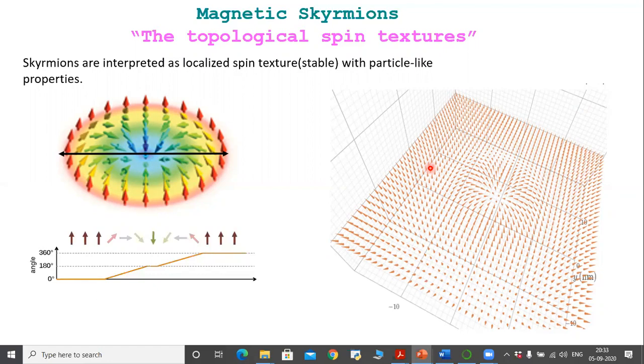Okay. So you are using a 2D film, I mean, only one layer of spin? Yes, one layer of film. This is actually a Néel skyrmion, found only in 2D films. There is another type of skyrmion called the Bloch skyrmion, which is found in bulk materials. Working with Néel skyrmions is much more efficient. So this one is a 2D film. Yes.